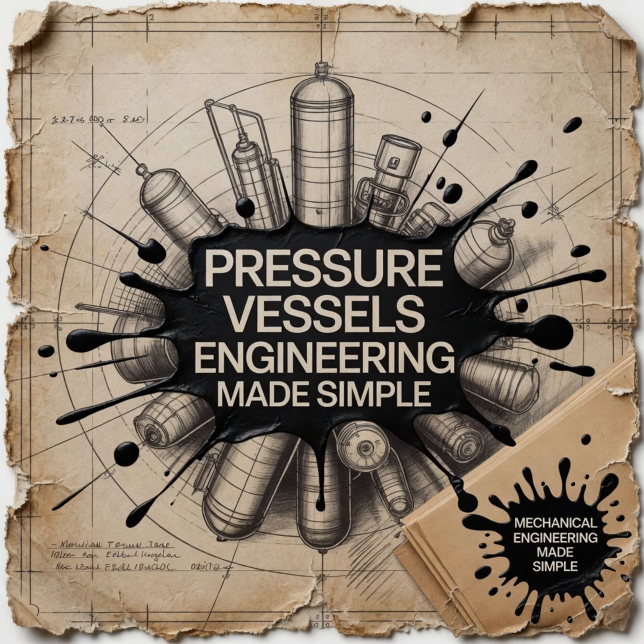And the uniform stress assumption just goes out the window. Completely. In a thick-walled vessel, the radial stress becomes a massive factor. And more importantly, the membrane stress is no longer uniform. The tension on the inside skin of the vessel is significantly higher than the tension on the outside skin. Oh, so it's uneven. Very uneven. The stress creates a steep gradient through the thickness of the steel. The math required to ensure the inner layers don't tear while the outer layers are barely doing any work is vastly more complex. But for the sake of our primary focus today, we are staying in the thin-walled uniform stress universe.